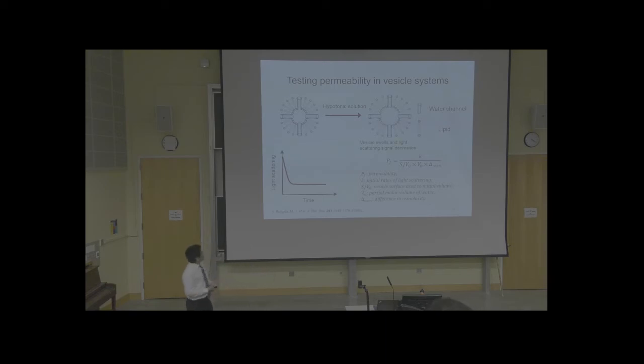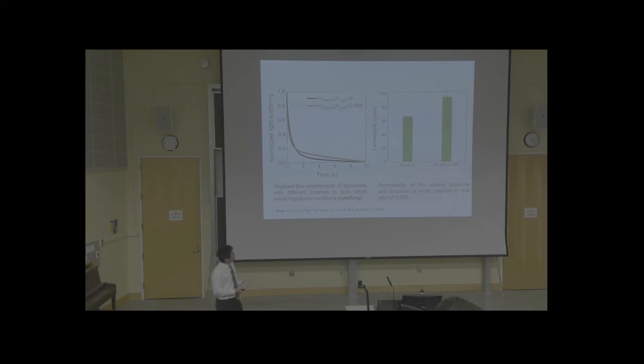So we incorporate our channel into vesicles. We first made a control pure lipid vesicle. Then we add the channel into vesicles. The channel to lipid ratio is 1 to 200. So we find that the kinetics is much faster. Then we calculate the permeabilities. We find the overall contribution from the channel itself compared to the control. So now we know our channel can really transport the water.